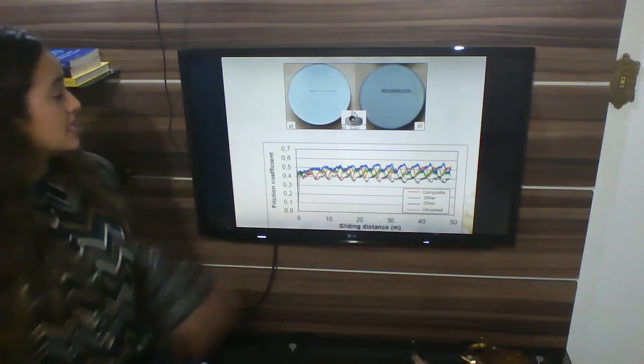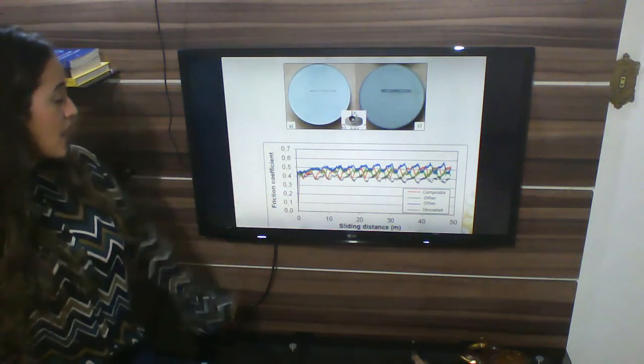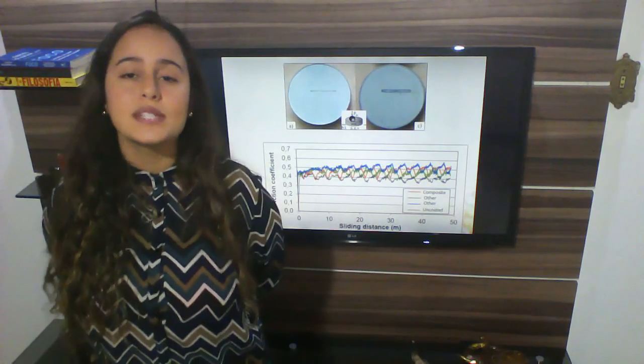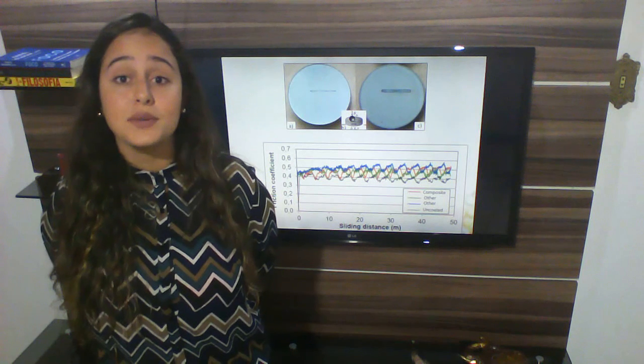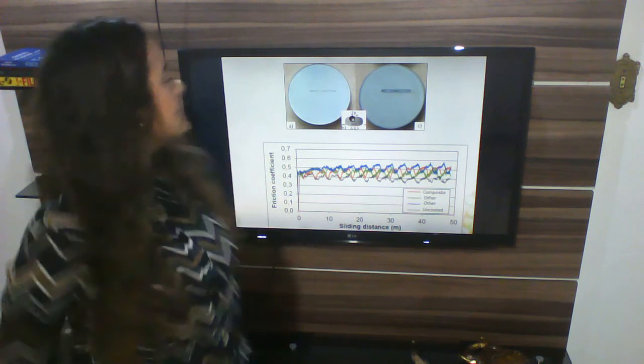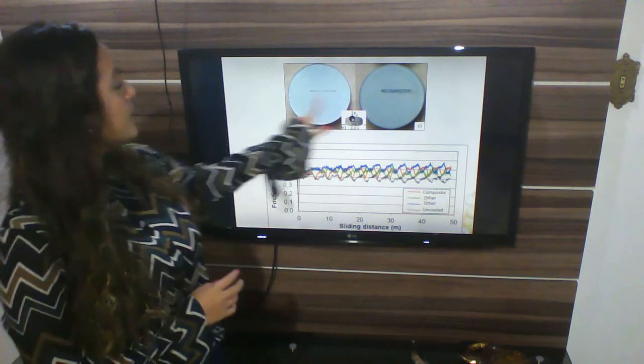The friction coefficient of the composite was between 0.4 and 0.5, which is above the lubricious regime of 0.2. The coating was prematurely broken, and then deformed, comminuted, and oxidized by the substrate and counterbody during the sliding test. The major contribution to the friction coefficient behavior was from the metallic substrate, but controlled by the formation of the third body. What was found is that the test conditions may have been too aggressive for this coating.